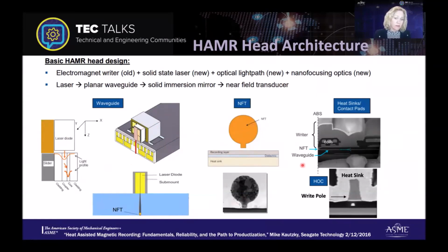As far as how this is integrated with the rest of the head, this is a side slice of the head. That waveguide is here. The near field transducer is very small at the bottom. It's put in close proximity to a write pole, so the magnetic field and the heated spot are very much in alignment. If we look at that from the disk, looking up in this direction, you just see that square end of the peg, and it's very close to the write pole. So again, we have magnetic field and heated spot very close to each other.